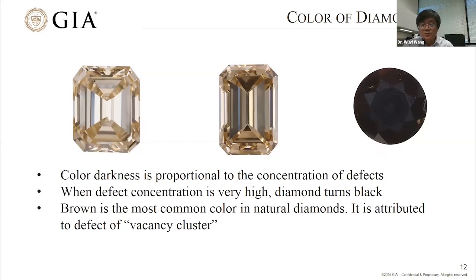Since brown color is so common and so important when we talk about treatment, I will mention a little bit about the brown color. It is also very common in CVD synthetics. We grow CVD reasonably fast and have some brown color, and that brown color, we still don't know for sure whether that's due to vacancy clusters or not. That could be different from the color origin of a natural diamond.